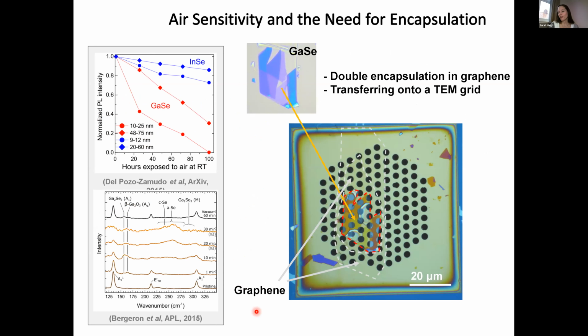And so I'm just going to mention that these have been produced in an argon glove box, and they're sandwiched together in an argon glove box, transferred onto a TEM grid, and then they're protected by two layers of graphene on top and bottom before we put them into the TEM, and that allows them to be as pristine as we can make them at the moment. There's been a huge development in Manchester, and Roman Gorbachev has now produced an ability to do this stacking in ultra high vacuum, and so we're really looking forward to the exciting types of new materials that we're going to be able to look at when the exfoliation happens in UHV.